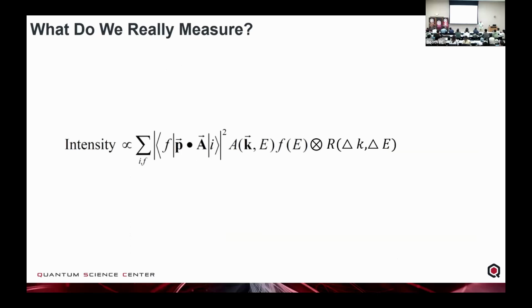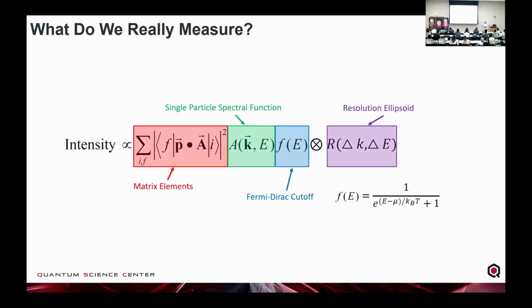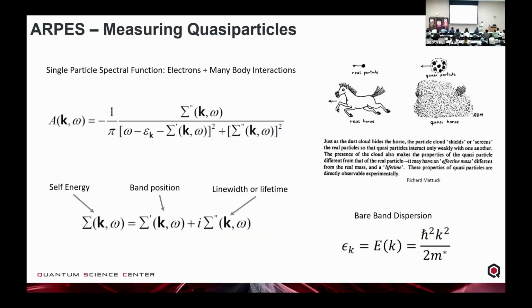So what is it we actually measure? This is what our intensity is proportional to. In this formula, we have matrix elements, which I'll get to, and we have our single particle spectral function. We have a Fermi-Dirac cutoff because we can only measure the electronic states below the Fermi level. And then we have this instrument resolution ellipsoid based on the energy and momentum resolution of our instrument.